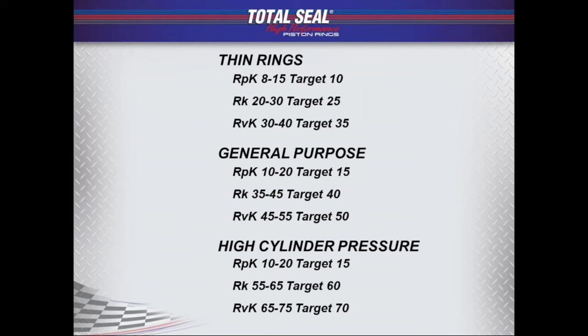If we start off with that RVK number too low to begin with, it's only going to go lower. So if I'm trying to get a target of say a 50, that window of 45 to 55, before I start my plateauing process, I better be in the 60s or 70s. It's almost always better to have that number be higher than lower because it's only going to go lower when you're plateauing. So if you've got that profilometer, stop at that step before you start plateauing and take a look at that RVK number. At that point, that's really the only number I'm concerned with, the RVK. If I want to be a 50 at the end, when I'm plateauing, I better be starting off around a 70 because that number's only coming down.